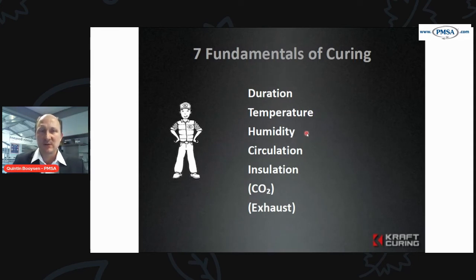Humidity is critical. We've spoken of that earlier. Concrete needs the humidity to allow the hydration to take place. Circulation to get even curing throughout. Insulation, critical, because if you're not insulating, we're losing all that heat. All the heat is being lost to the environment. So a good insulated curing system is critical.